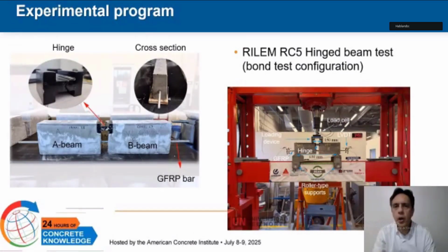During casting, a block of expanded polystyrene was temporarily inserted to create the hinge void. After curing, the placeholder was removed and replaced with a steel hinge, which allows for free rotation and induces a pure bending moment at mid-span. A single GFRP bar runs continuously through both beams and is partially bonded over a defined length, and the bond region is carefully controlled using plastic sleeves that isolate the bonded segment.